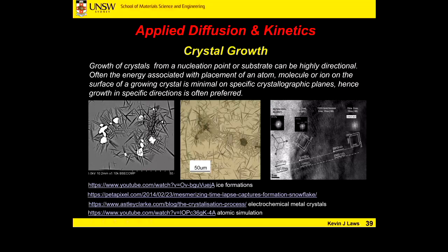But from these particles, you can see that they are coming off in some very, very specific directions. That one there is a nice example. Okay, we've got a nice little cubic Y2O3 particle. We can see a phase growing very rapidly in one direction from that particle. That phase is actually alpha magnesium.